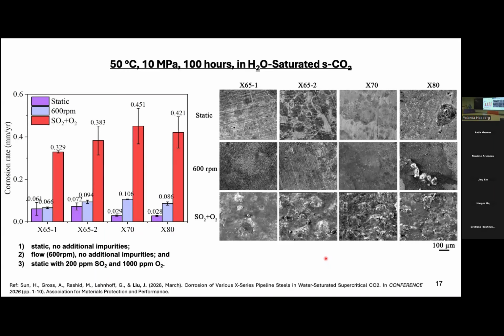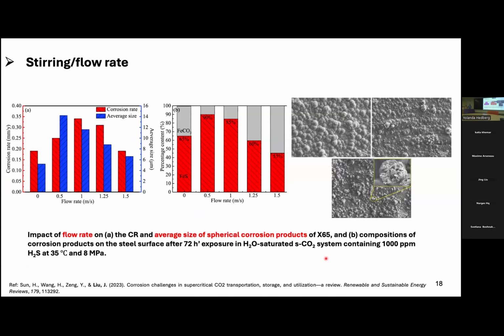And if we introduce impurity, it is always more aggressive than, for example, 600 RPM. So when we try to explain this data, we checked other people's publications. From here, you could tell that when you have a static condition up until the flow rate, they convert the RPM to meter per second. In the beginning, as the flow increases, the corrosion rate increases with flow rate. But if you rotate it even faster, the corrosion rate will start dropping.